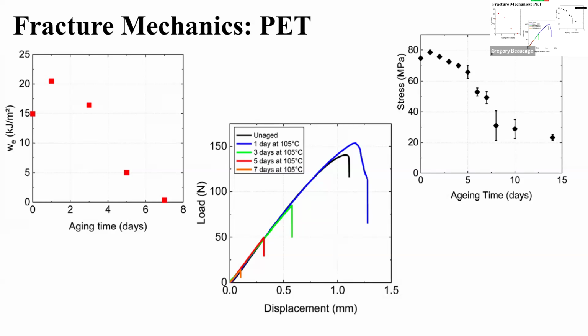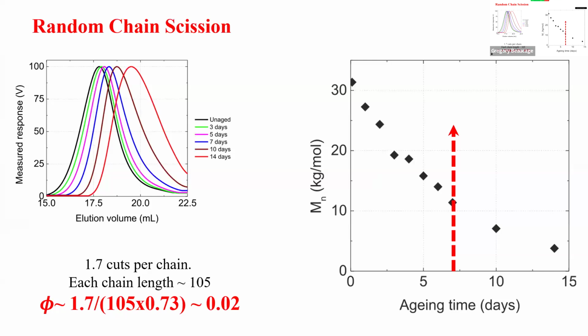So it's telling you there's a deep connection between breaking bonds and getting to failure. And when you start reaching failure, you make micro nanoplastic. So it's very simple. The material is starting to lose integrity because the amorphous phase tie chains are getting cut off. That makes my micro nanoplastic. Everybody happy so far? Do I want to keep on talking?